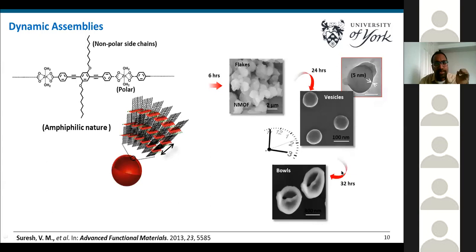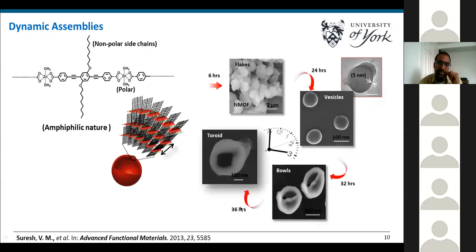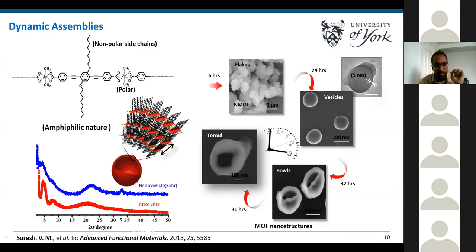Now, on increasing the reaction time to 32 hours, we see nanobowl formation, and then finally toroid nanostructures at 36 hours. So, due to the dynamic nature of the coordination chains along with the hydrophobic moieties, it is possible to create such a large number of MOF nanostructures within a single system. And the integrity of the MOF is maintained in all the structures, as evident from powder X-ray diffraction analysis.